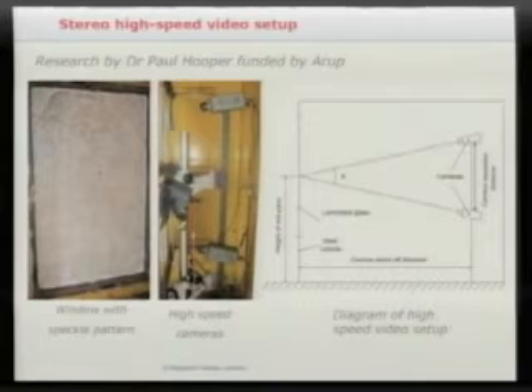And so this is research done by Dr. Paul Hooper, supported by ARUP. And we use two high-speed cameras with an appropriate triangulation angle. And you can see here, if you look on the rear face of the laminated glass sheet, you can see what's effectively a very fine distribution of dots. In fact, they're quite big. At this scale, the panel is big, and that means that those speckles need to be quite coarse.